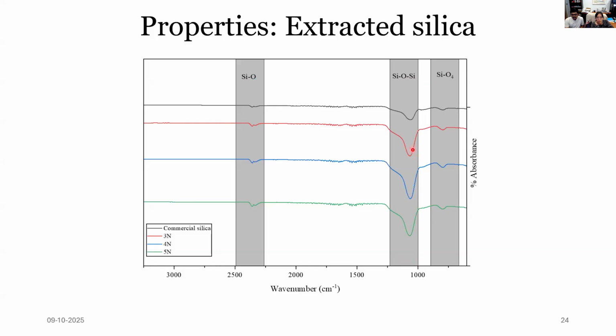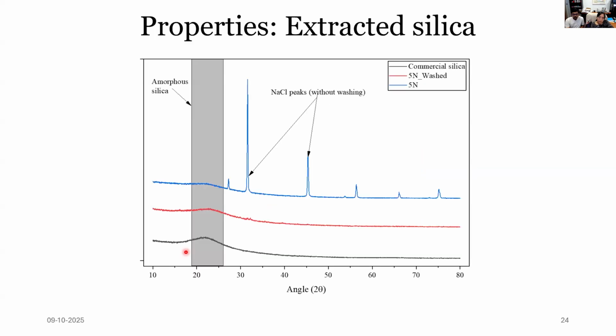And we could also see that the intensity increases as we increase the normality of the system more and more. And to confirm whether we have any impurities in the system other than the silica, we did an XRD analysis. Initially, when we used the silica as synthesized from 5 normality without any water washing after the synthesis, we could see a lot of deposits of sodium chloride in the system. So in order to remove the sodium chloride, we washed again with water 2 to 3 times to get rid of the NaCl, and then we could get the amorphous silica from the system, which is comparable to the commercial silica that we had.